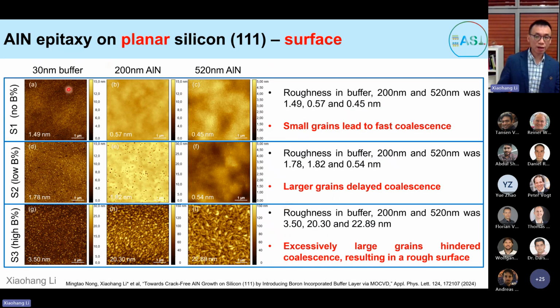And here we have the AFM study of the 3 samples at different stages of the growth. For the buffer, this is the aluminum nitride buffer, it has the smallest grain size. When you have a little bit of boron in it, you start to make the grain size bigger, reflected by the higher roughness. And then for the highest boron flow, you have the roughest surface. So this is the buffer: aluminum nitride, low boron, boron aluminum nitride, and high boron, boron aluminum nitride.